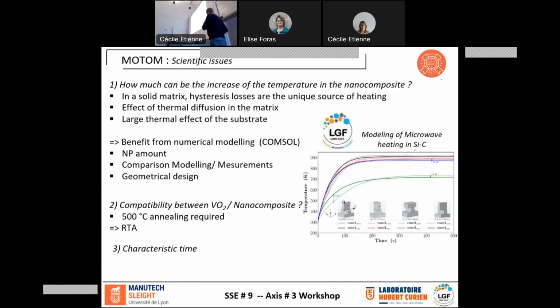So in that project, there are, as I said before, different scientific issues. The first is not so evident: how much can be the increase of the temperature in the nanocomposite? In fact, in a solid matrix, only the hysteresis loss can give a heating. There is no stirring, so it will really change the situation. And we don't really know the effect of the matrix in terms of thermal diffusion. The porosity will play a role on the thermal diffusion for sure. And what can be the effect also of the substrate.